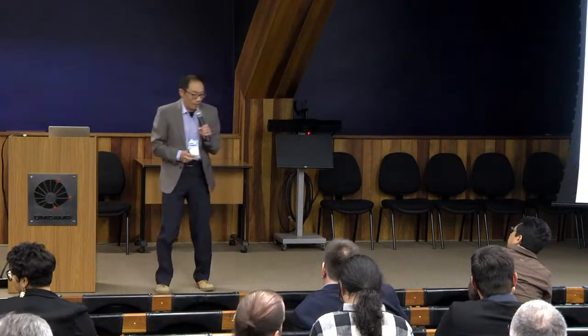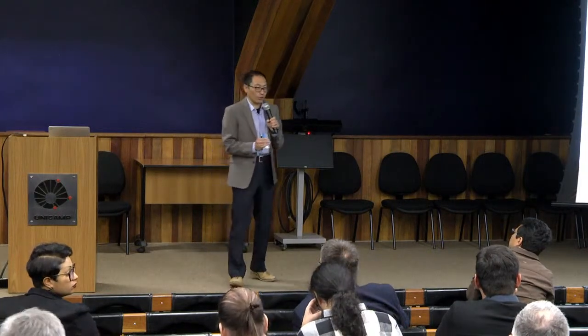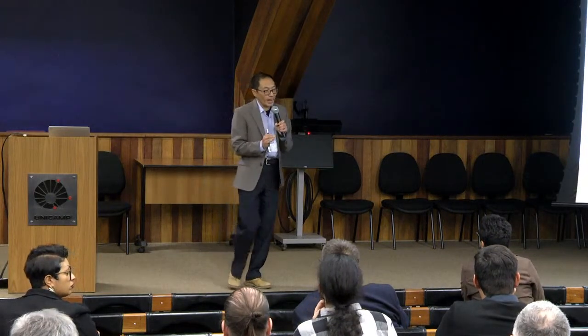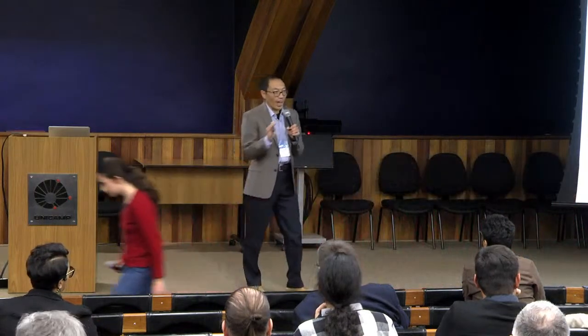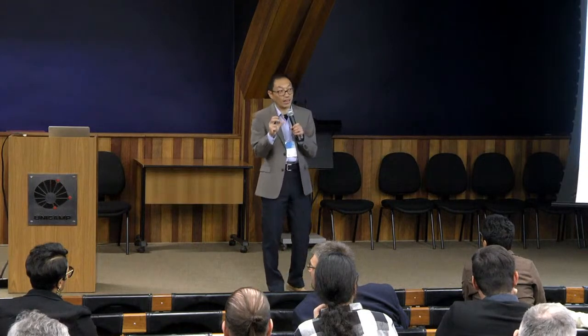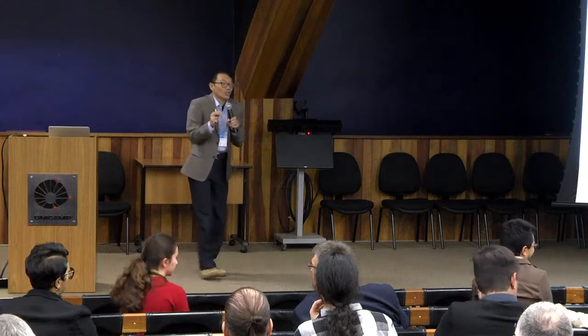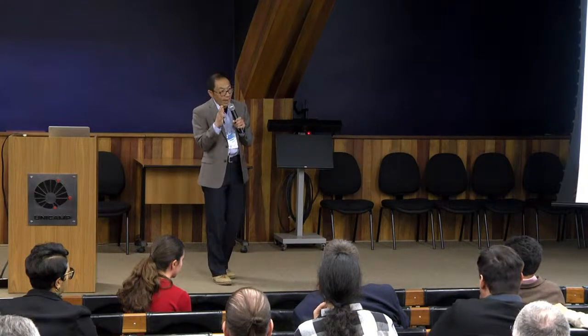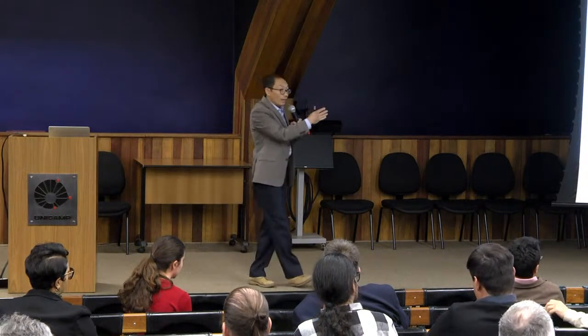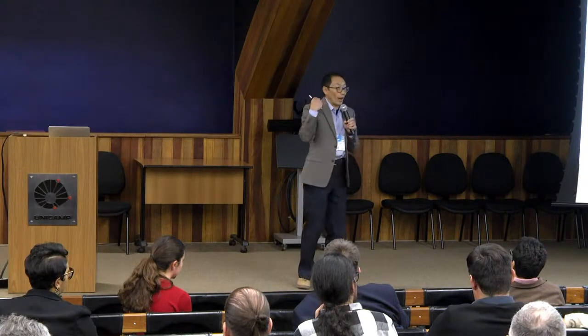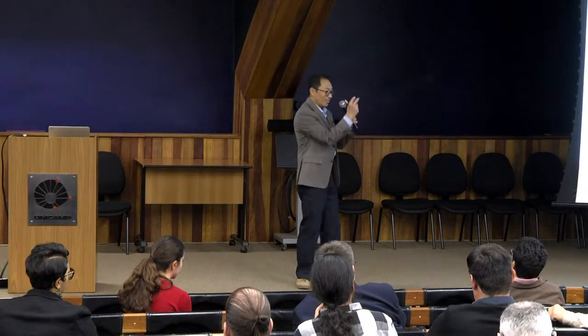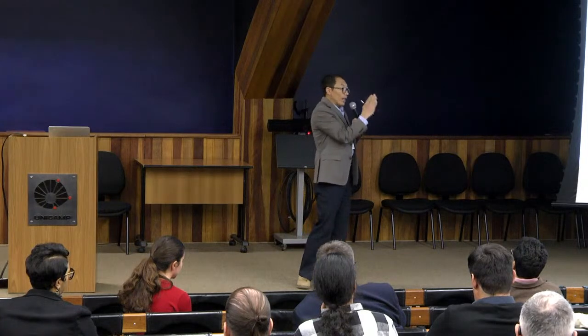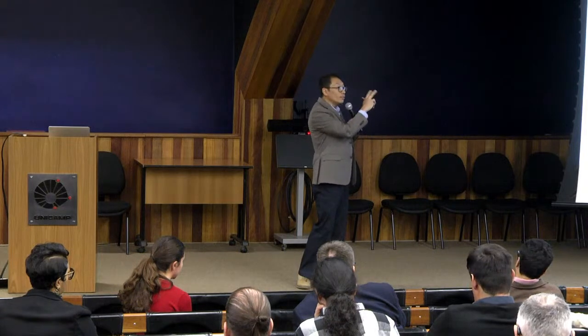Excellent. John, I'm happy you asked this question. One thing I should mention is that in the academic field, the majority of the work is done on the electrode. In the industry field, 90% of the R&D is on the electrolyte. Every commercial battery you are using right now has more than 20 additives in the electrolyte, and every company has a different formula, and they never even file a patent. It's a top commercial secret. Different additives affect the interface formation between the electrode and the electrolyte, and that interface and surface, you are absolutely right, affects the redox process. It sounds separate, but they are linked. What kind of surface you have affects what kind of bulk redox, especially on the oxygen.